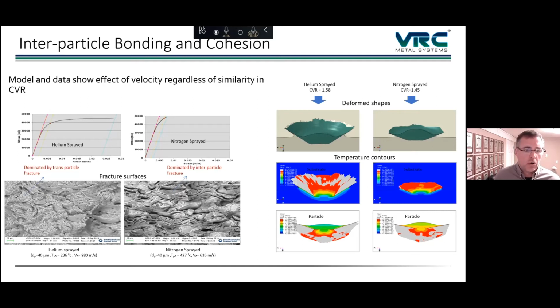So even though the temperature itself brings that critical velocity ratio up to similar values as the helium, the particle itself is where all the deformation is occurring because the particles are so hot. The substrate is not seeing as much of that deformation, and that limits the amount of bonding. So you need plasticity of the particle and the substrate to get that really high quality bond.